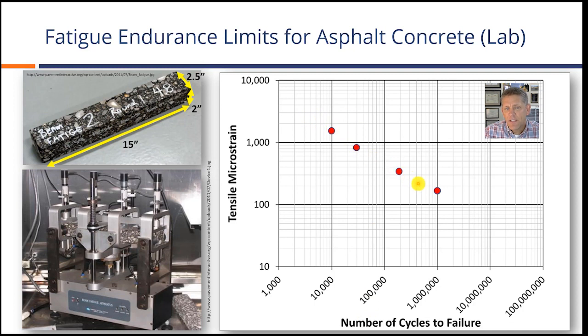And this type of testing has been done since the 1960s. Lots of studies have been done over the years, and they mostly have in common that you do it over a range of strain levels, and then you fit a curve to that data set and you just extrapolate it down and you extrapolate it up. But what that ignores is the fact that most materials, and asphalt concrete included, have an endurance limit, a strain level below which you will not induce damage.